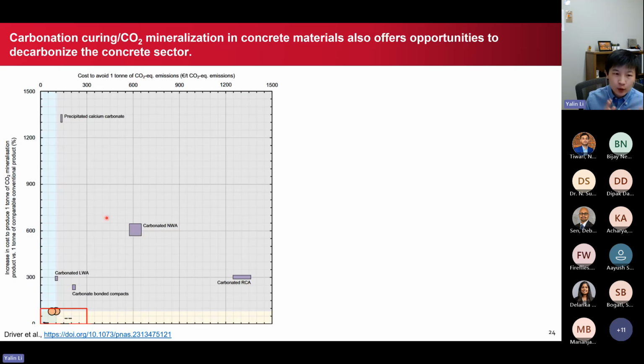Okay, and all those are the concrete recycling technologies. But one part that I didn't mention actually has quite some potential in decarbonizing concrete materials, essentially through the carbonation process. As we mentioned, one big part of the emissions associated with cement is from the calcination process, where you emit carbon dioxide at a 1-to-1 ratio when you start with limestone, which is essentially calcium carbonate.